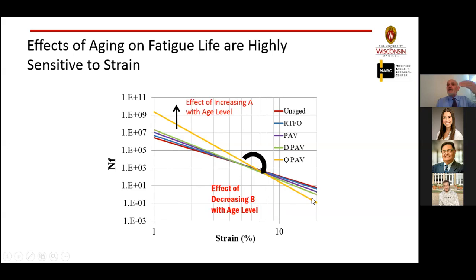Now, this is a binder run as Unaged, RTFO, PAV, a double PAV, and quadruple PAV. And you see the consistency in this behavior, which really tells us the importance of the strain spectrum, and the lack of focus on the strain could get us in trouble. Like saying, well, I aged the material, it becomes stronger.